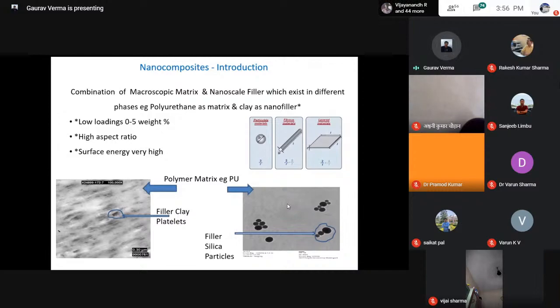But if you want to get consistent results, we have to ensure that the loadings used are in very small quantities, so that you do not allow aggregation of these nanomaterials, because they do have a tendency to aggregate. That is a natural tendency to get into a micron scale feature, and I'll show you why it happens. And if you do not have that high aspect ratio, that is why I have put a star around these observations, the surface energy which you encounter in the end is not very high, and it will not make desirable changes in the matrix.